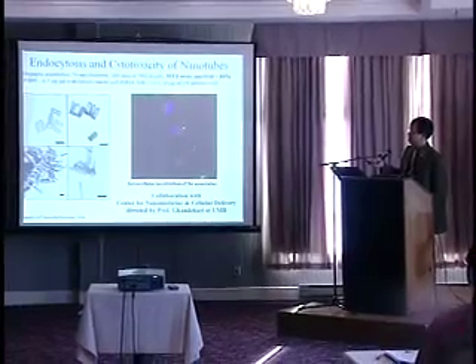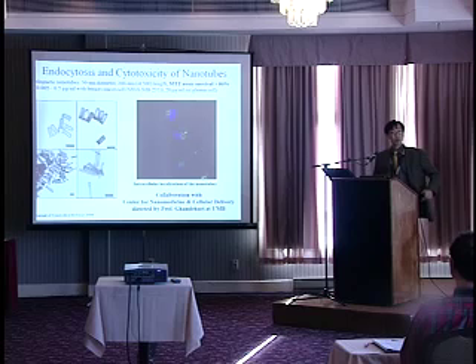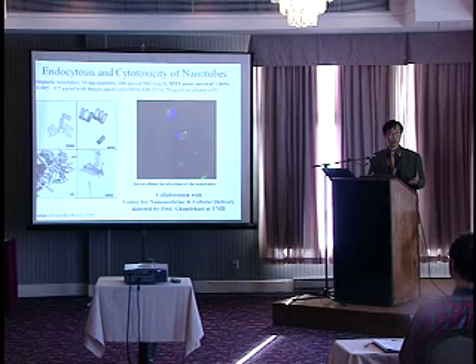However, when you look at these TEM images of magnetic nanotubes, these are the magnetic nanotubes here. They are about 50 nanometers in diameter and 200 nanometers in length, relatively large compared to other nanoparticles. So the first question that we had was, can this nanotube really be internalized into the cells, or does it just stay on the outer surface of the cells? And that was our first question.